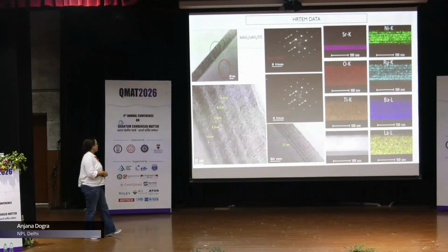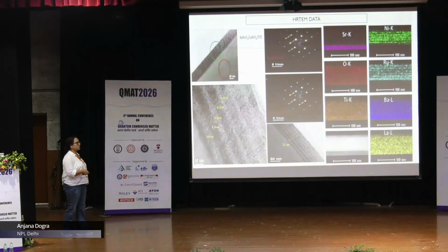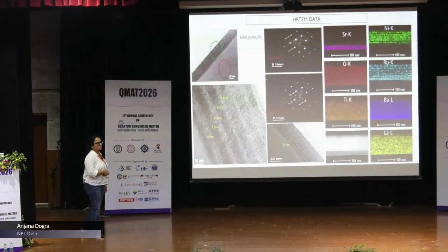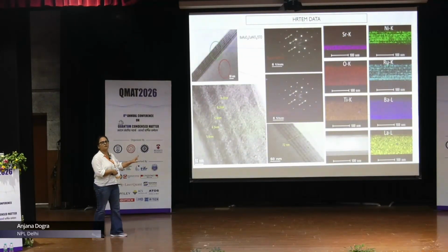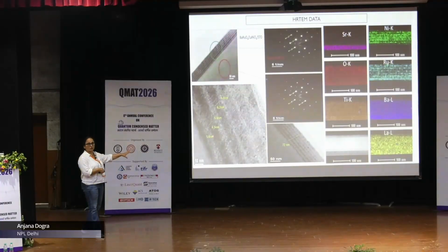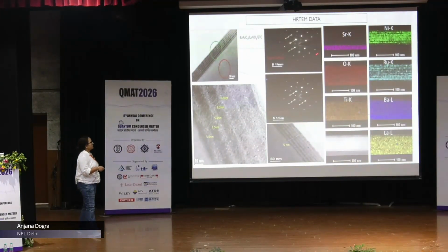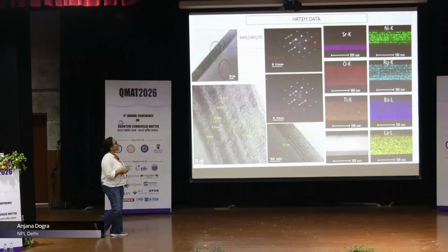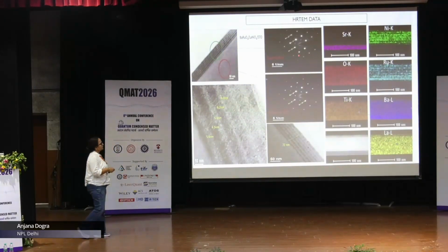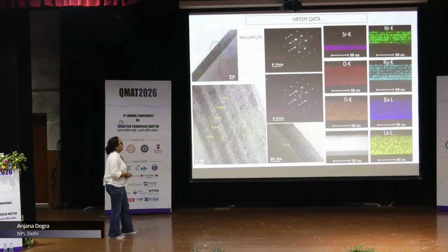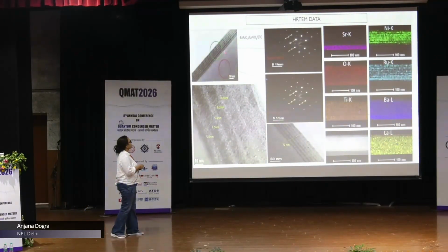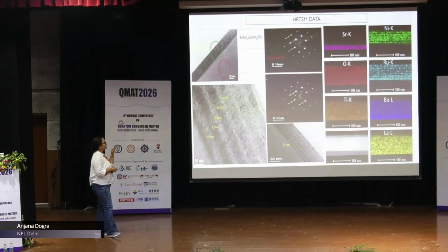We were taking 5 and 6 nanometers for BRO and LNO, and from cross-sectional TEM we could find that they match the thickness we had already deposited. And this FFT pattern also shows a good structure for these kinds of sublayers.